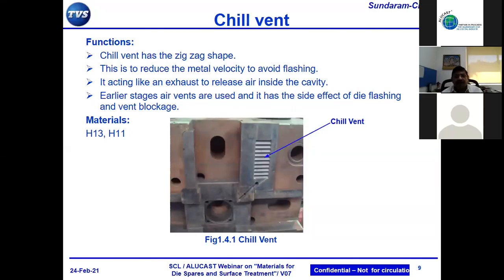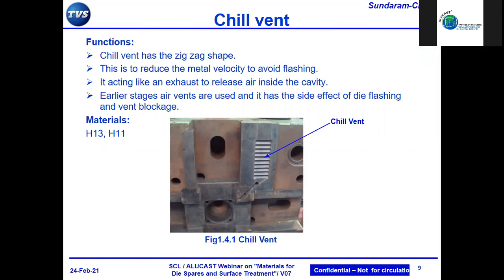conductive, which could enable quick solidification of the metal, and at the same time it should withstand that kind of heat and the wear that happens in the material. So I'll go into details of this, but the interface between the metal, the liquid metal, and the chill vent is normally H13 or H11, and we also use some of the copper-based materials here, which are composite with this kind of H13 initially.